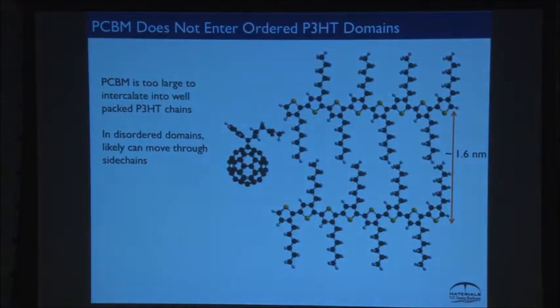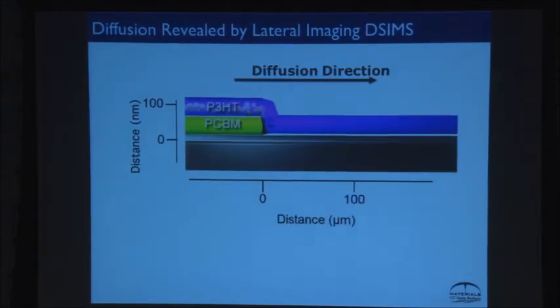When you look at that, we also have been saying, well, it doesn't go in the crystalline phase. And people don't have trouble wrapping their head around that sometimes. If I look at the ordered part, just as a cartoon, the chains line up a bit like this. The fullerene is about this size. And so basically, there's no space for this fullerene to make it in the ordered chains. The disordered region, you can imagine this chain is pretty flexible. It wraps around. And the fullerene can just kind of dissolve into the side chains, we think. But it's hard to prove exactly where it's at. We can also do this other ways. You're kind of beating this into the ground at this point.